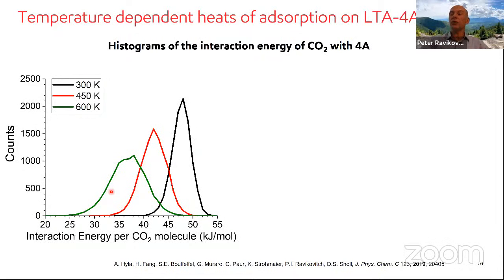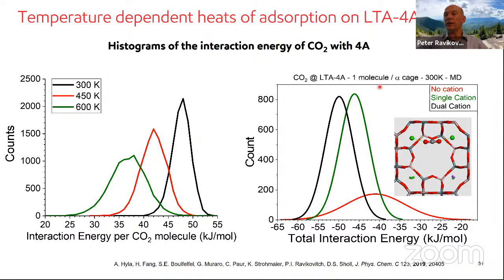Average. You can also plot the interaction energies for different sites. You can identify within these LTA type zeolites three types of sites. You can identify so-called dual cation sites, when CO2 actually interacts with two cations, and this is the highest energy. You can also identify so-called single cation sites, when the CO2 interacts with one cation. And also you can identify just a CO2 which is adsorbed somewhere in the middle of the cage, which has the lowest interaction energy. So what's going on?